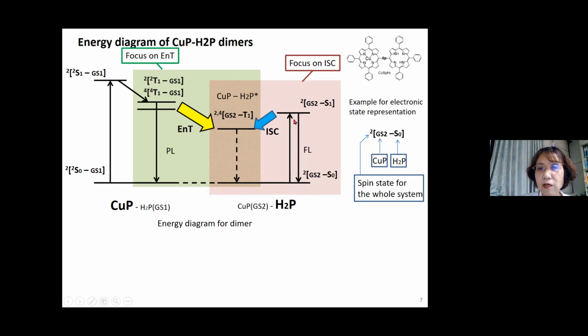Alternatively, if we excite free base porphyrin, we can yield the excited singlet state of the free base, but the whole system is a doublet state because the copper porphyrin is a doublet state. Then the dimer undergoes intersystem crossing and produces the triplet state of the free base. Here, copper porphyrin is in the ground state, the free base porphyrin is in the triplet state, and the total spin state is a mixture of the doublet and quartet. Both processes cause the same excited state, where free base porphyrin is a triplet and copper porphyrin is in the ground state, and the doublet spin and the triplet spin of the free base are weakly coupled.